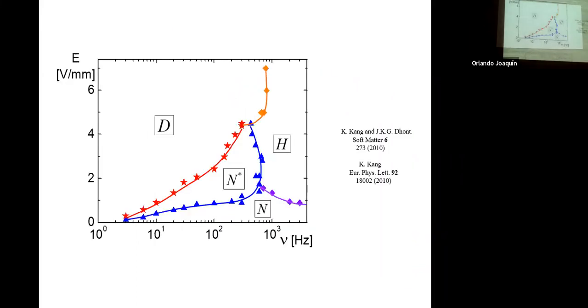So this is how the phase diagram looks. So this is the electric field strength, volts per millimeter, and this is the frequency of the field. And you see a number of phases. Now at zero field, you have this normal nematic in equilibrium with an isotropic phase.